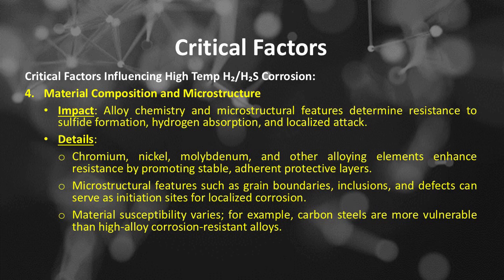Critical factors. Number 4 is material composition and microstructure. The material composition and microstructure impact. Alloy chemistry and microstructural features determine resistance to sulfide formation, hydrogen absorption, and localized attack. For details, chromium, nickel, molybdenum, and other alloying elements enhance resistance by promoting stable, adherent protective layers. Microstructural features such as grain boundaries, inclusions, and defects can serve as initiation sites for localized corrosion. Material susceptibility varies. For example, carbon steels are more vulnerable than high-alloy corrosion-resistant alloys. Critical factors.